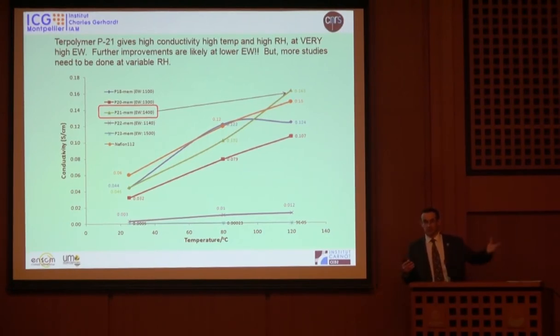Because sometimes, if you do your experiment here in your lab, with the same membrane and the same conditions, but over relative humidity and temperature, you can find different conductivities. So it is very important to be reproducible here.